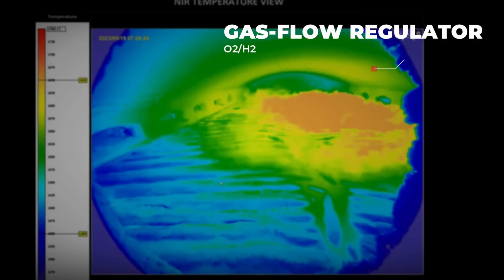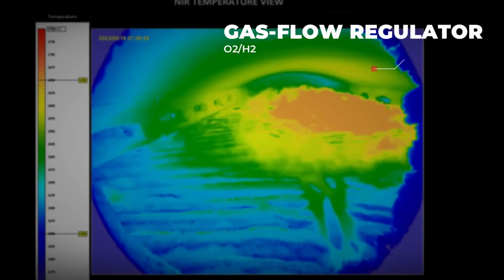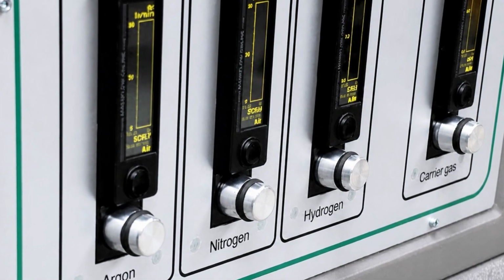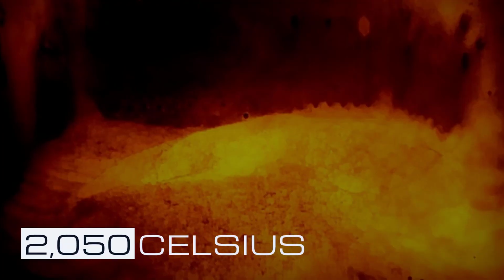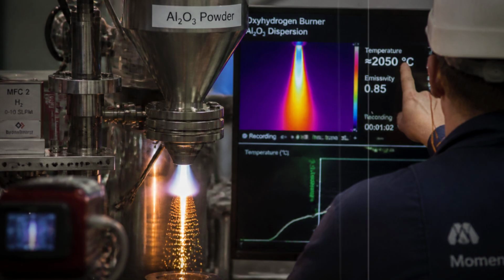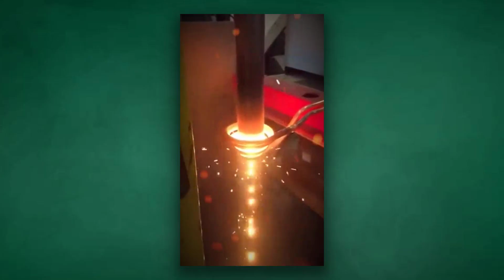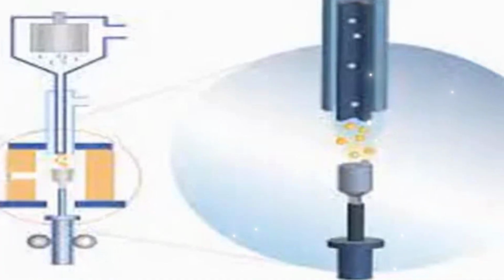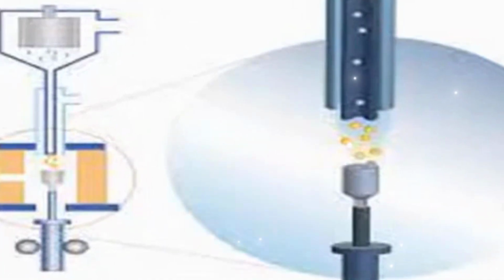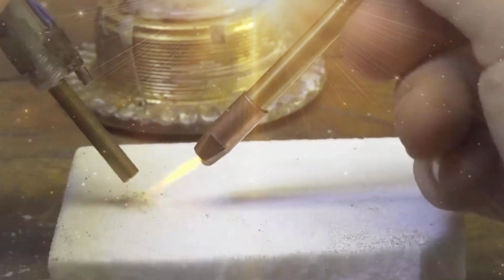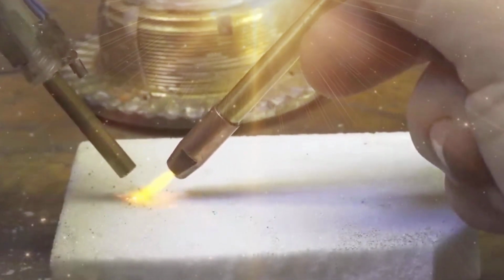Precise gas flow regulators monitor the oxygen to hydrogen ratio in real time, keeping the thermal envelope stable. Because pure aluminum oxide melts at approximately 2050 degrees Celsius, this intense heat liquefies the falling powder instantly. The individual grains of alumina and chromium oxide fuse in mid-air, transforming into microscopic droplets of molten corundum that descend through the center of the furnace.